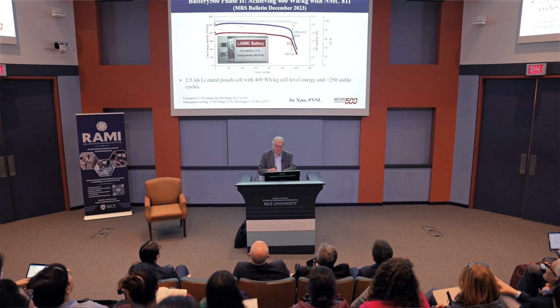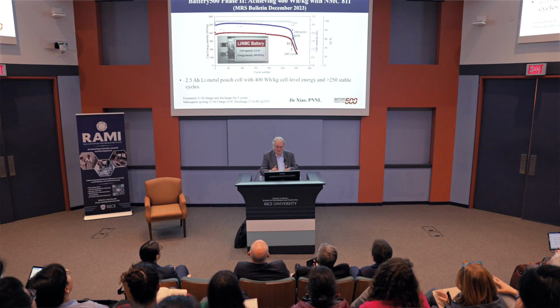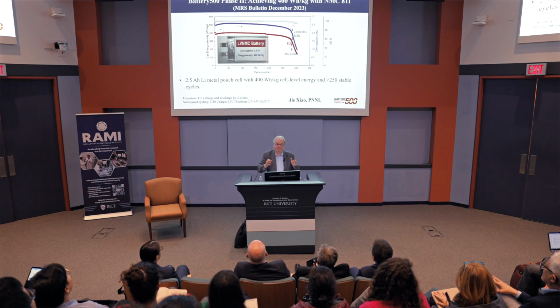No details here, because now we're above 350 watt hours per kilogram, which means it's export controlled. So we can't give details, they can't describe how they made these cells. In fact, we've got some of these cells now up to 500 watt hours per kilogram. So we can get high energy density, but we're getting fewer and fewer cycles as we go to higher and higher energy densities.